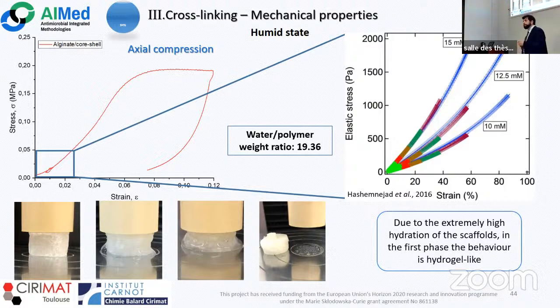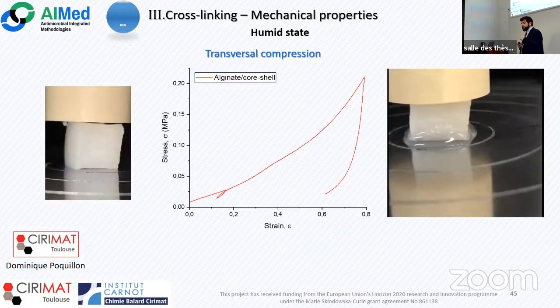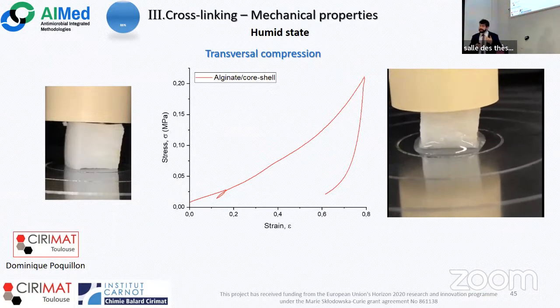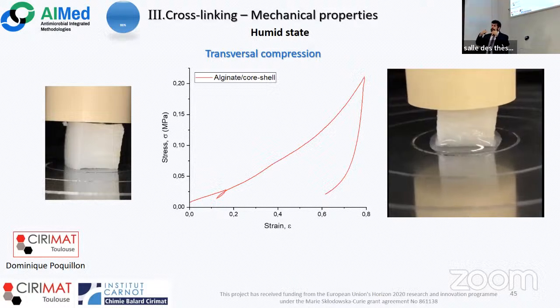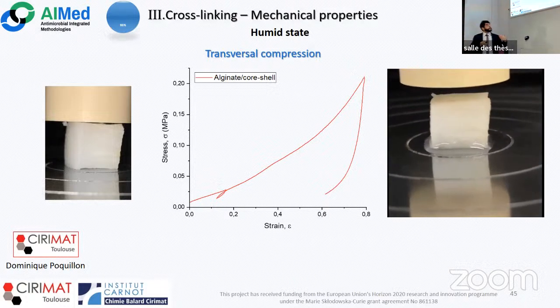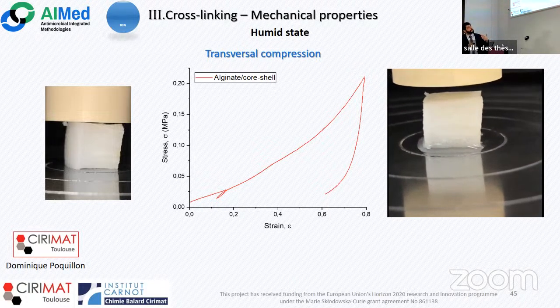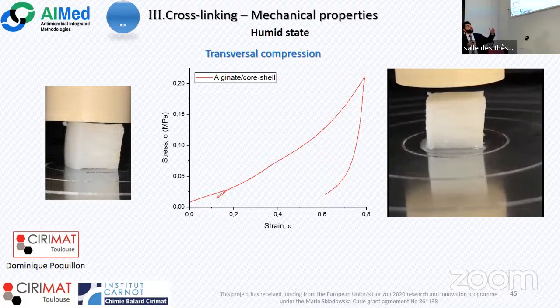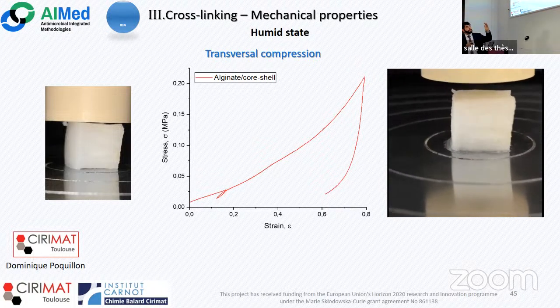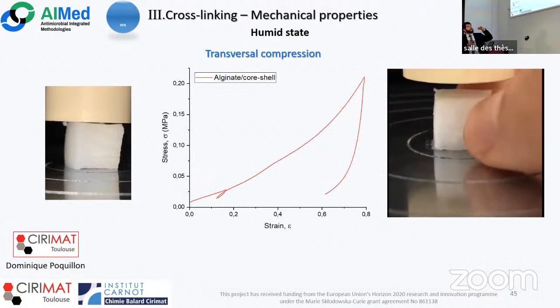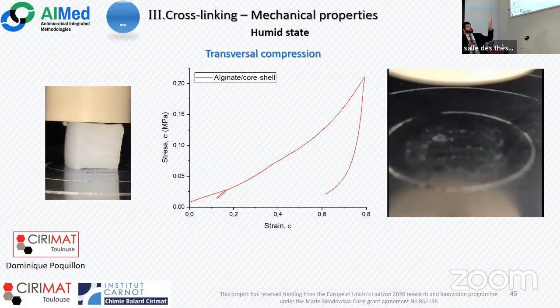This kind of behavior was also corroborated, even more enhanced, by the transversal compression. But in the case of this transversal compression, having a cube with all the pores open, the most interesting aspect is that, as you can see in the video, we pour out all the liquid, and even though we have a damaged structure, we reabsorb almost everything.